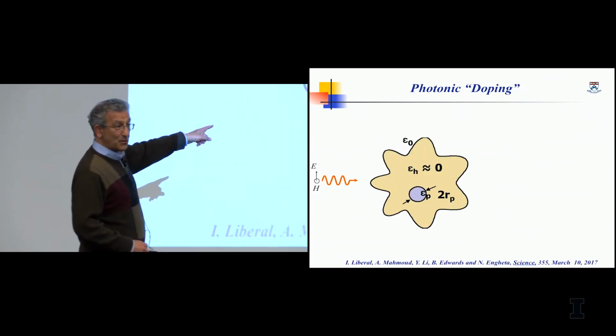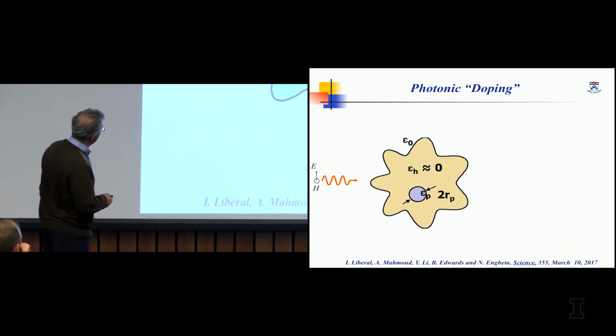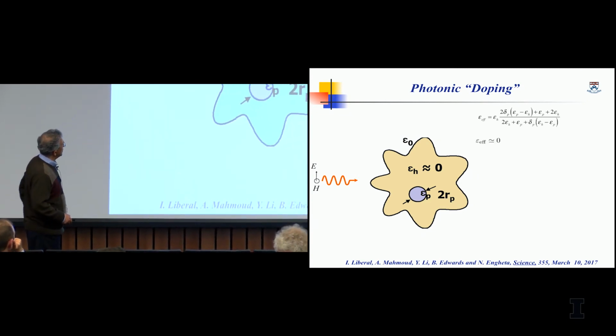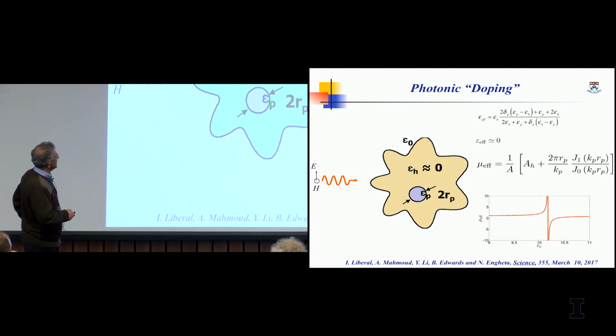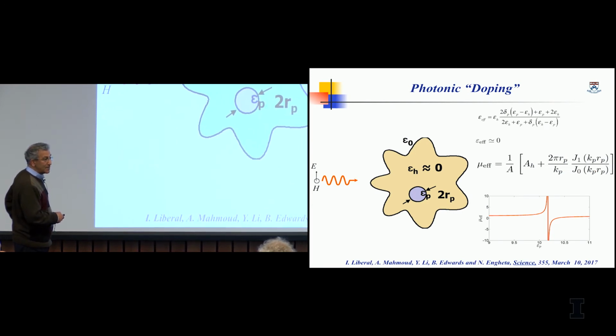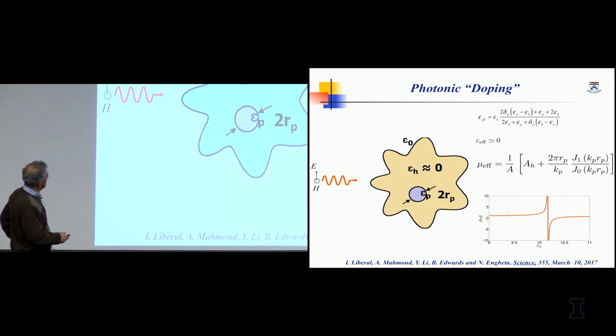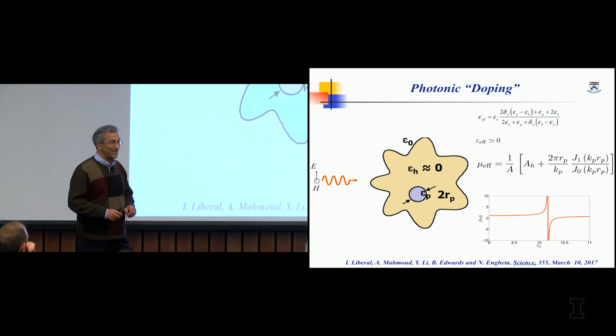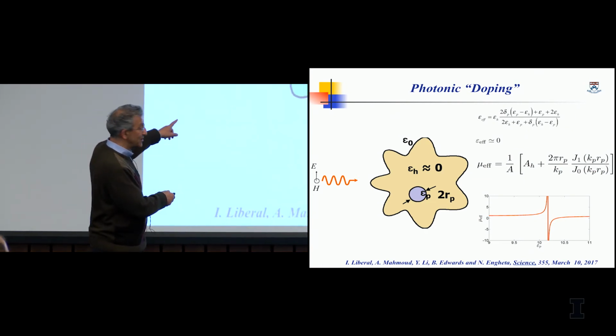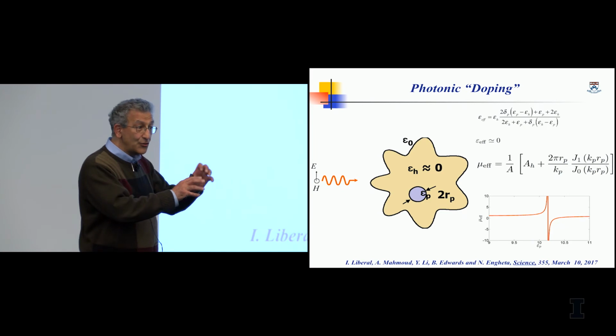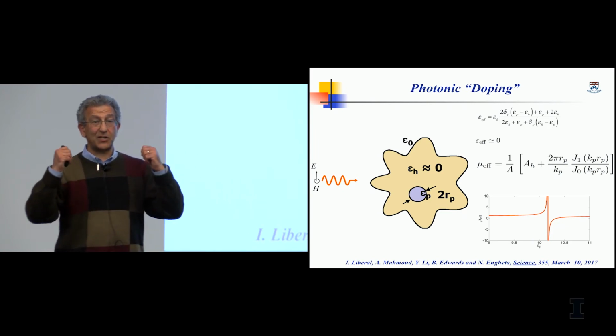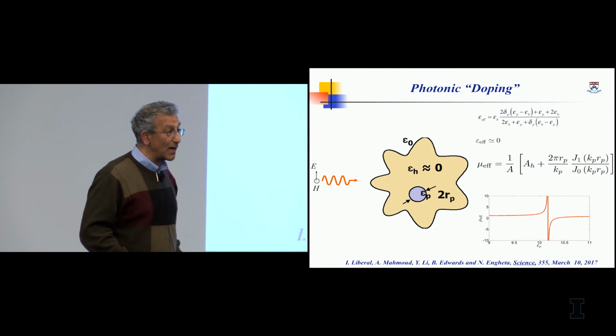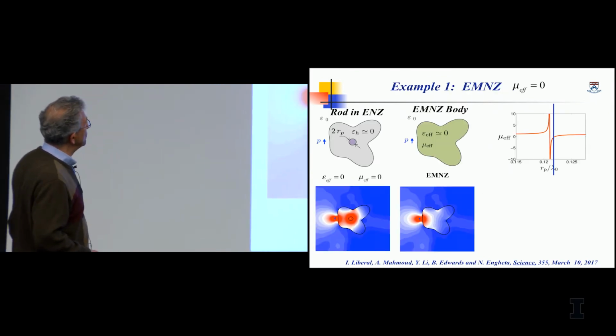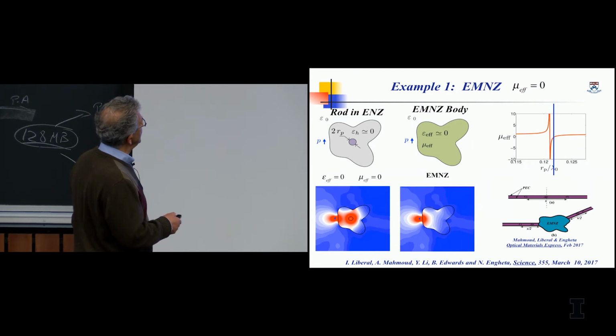So if I go to this structure, which I call photonic doping, and I put one dielectric rod over here, you can show that even though you add this dielectric rod, the effective permittivity from outside does not change, but instead the effective mu does change. Now, this is interesting. In other words, none of these materials are magnetic, and yet you combine them in a very interesting way, and to the outside observer, it looks like a different mu. You can have mu very high. You can have mu very close to zero. So for example, in this case, we designed this structure such that the effective mu is also near zero.